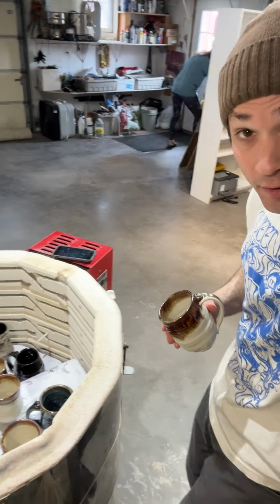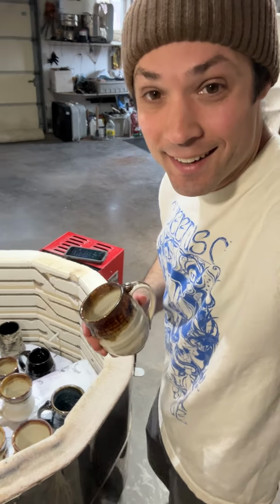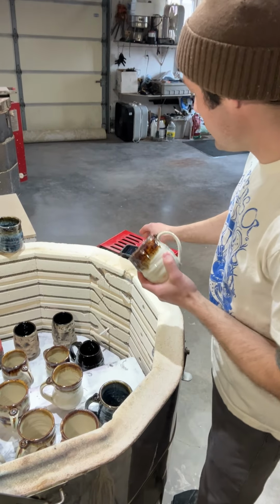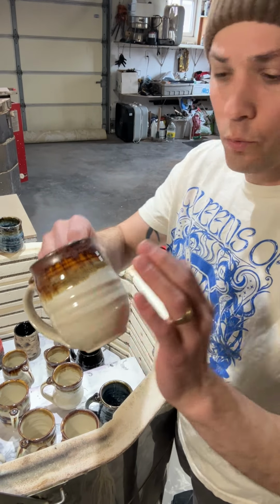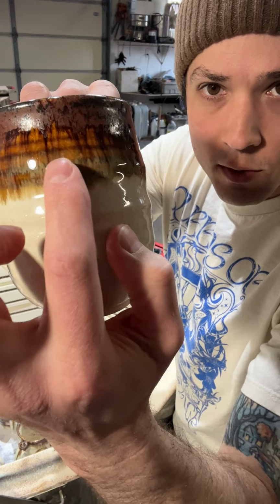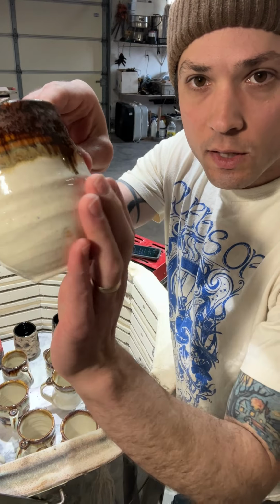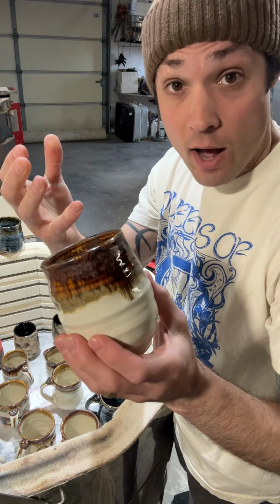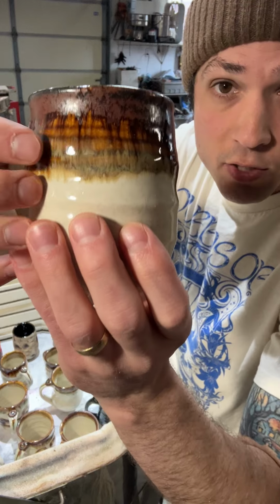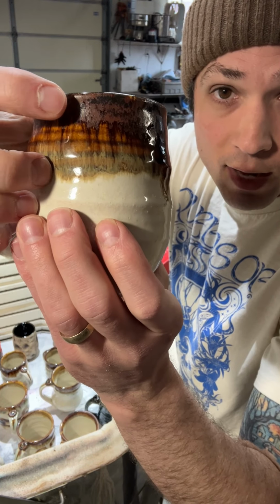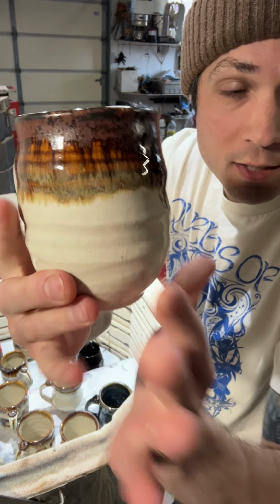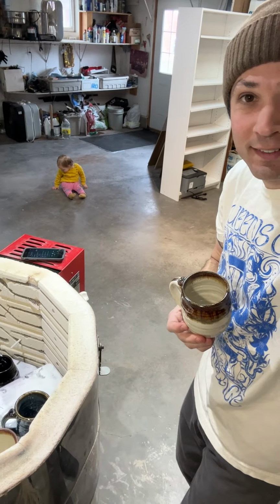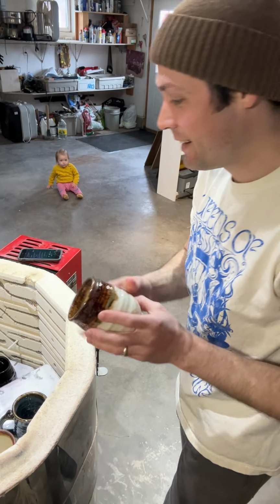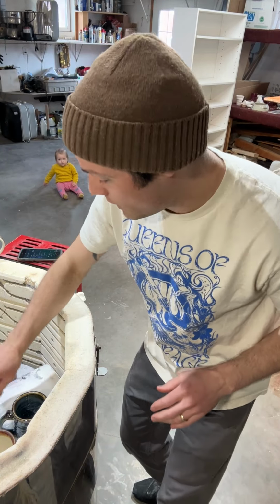This ash material gives the glaze really rustic qualities, like this transparency. This is the ash glaze, and the top is iron oxide. Iron interacts with the ashes, and it's giving it a transparency, and then kind of a matte surface, and then this golden yellows. And that's the magic ingredient here.